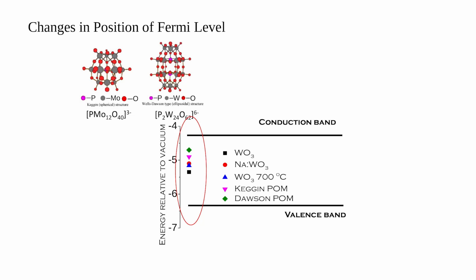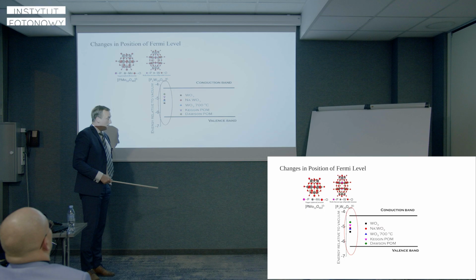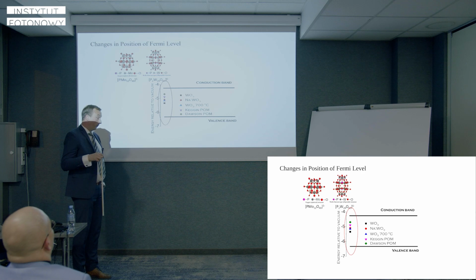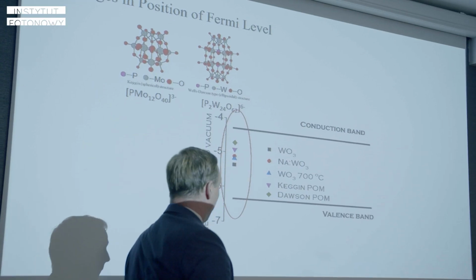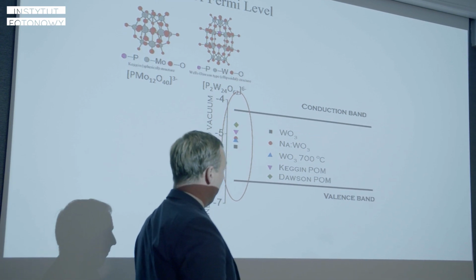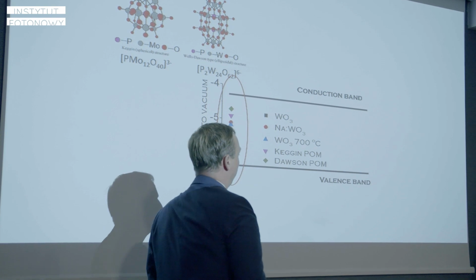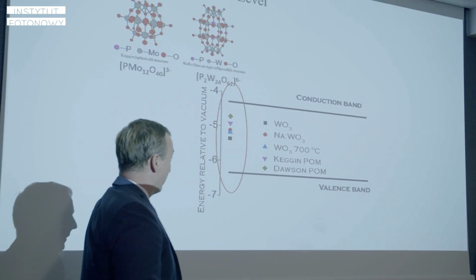This is the second very interesting observation. We used Kelvin probe measurement to see the level of the work function of our system after the modification of the structure. And for the Dawson type polyoxometalate, the work function had the lowest value.